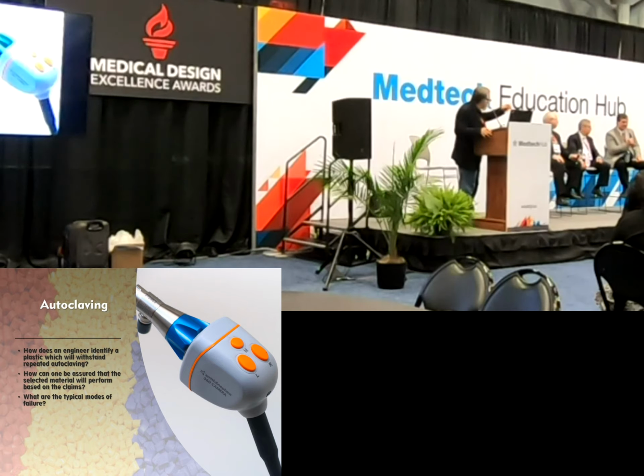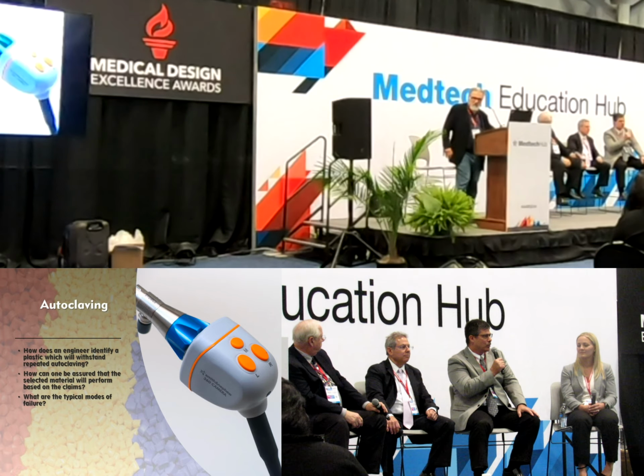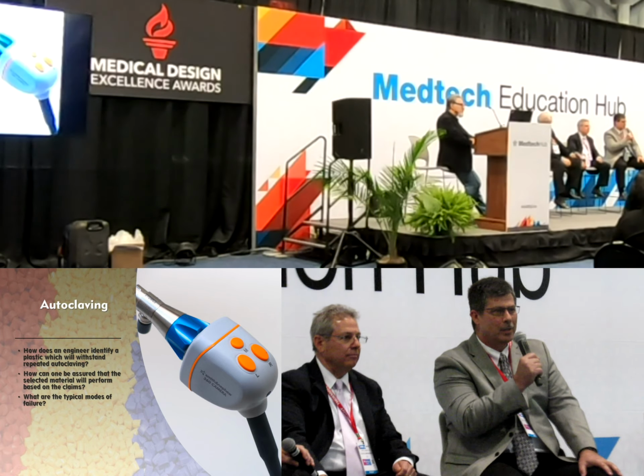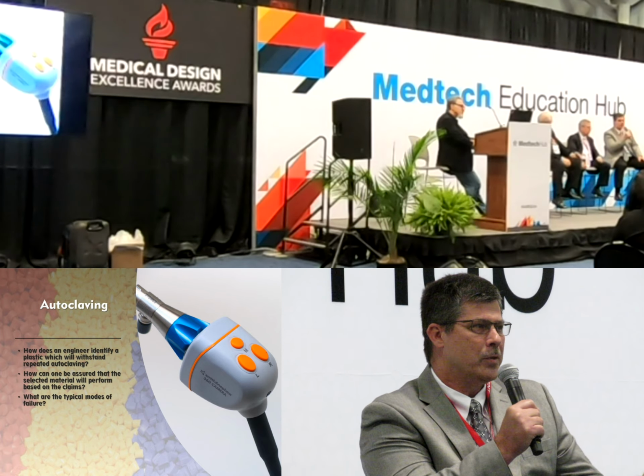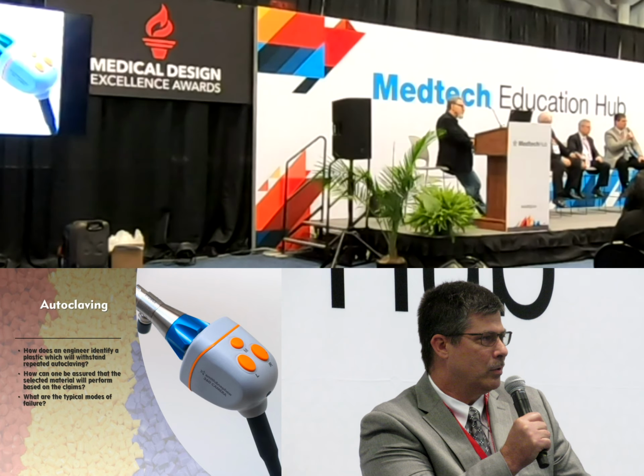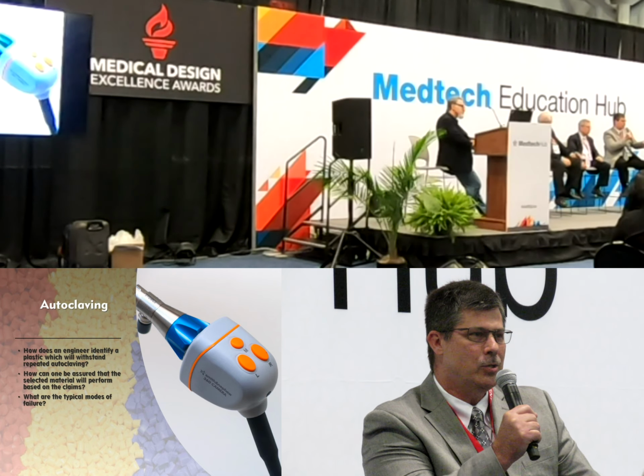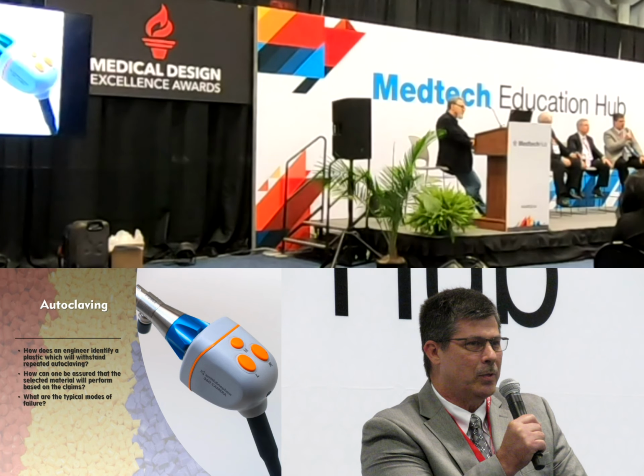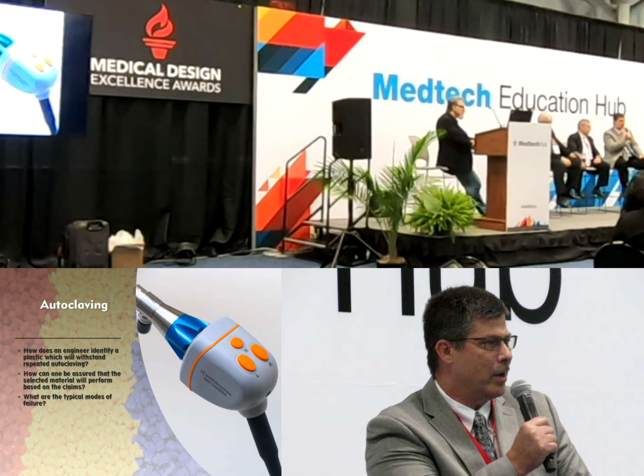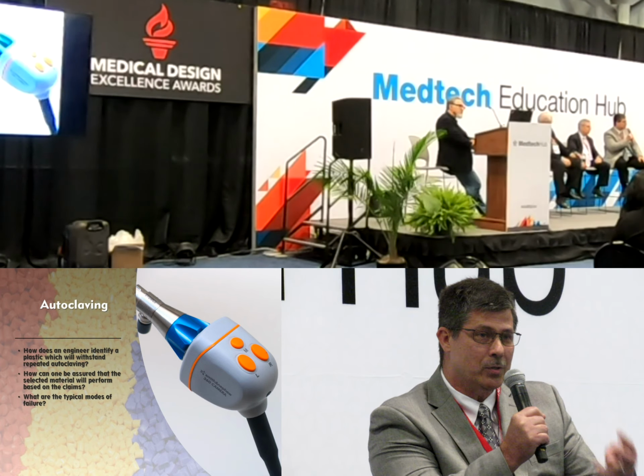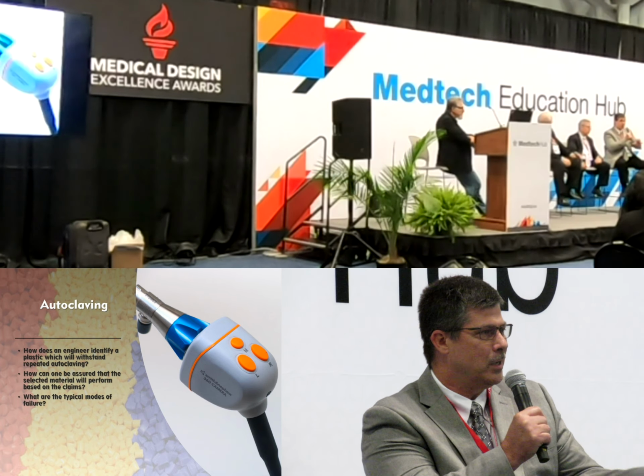Well, first and foremost, there's a smaller number of materials that can really truly be exposed to autoclave. There are crystalline materials that have a higher crystalline melting point that can certainly stand up to these higher temperatures. In the amorphous plastics arena, it's going to be based on the thermal glass transition temperature. We call it Tg. And typically you're going to have to be well above around 150 centigrade or higher to be exposed to the two types of autoclave, which are typically 135C and 121C. And that limits the number of materials you can look at.